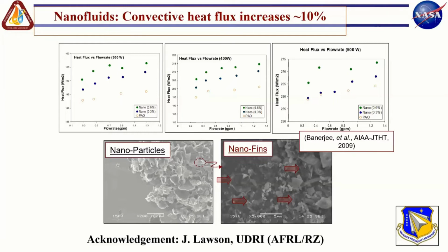But on closer examination of the surface of these fins, these micro fins or millimeter scale fins, we found that these exfoliated graphite nanoparticles, which look like these transparent glass pieces marked by the arrow on the bottom right, were sticking out like nanofins. So in other words, the nanoparticles were precipitating on the heat exchanger surface and giving you an additional surface area for heat exchange. So you have a millimeter scale fin, which is decorated with nanoscale fins on their surfaces. And so that could be thought of as one mechanism for increasing the convective heat flux.